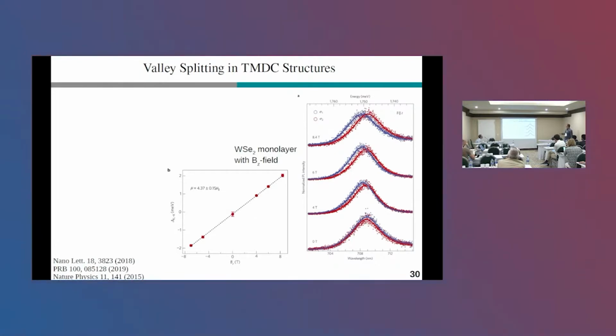Once you crank up the external magnetic field in the out-of-plane direction, you will find a very nice splitting of these two peaks, which is known as the valley splitting. And this valley splitting follows a linear trace as a function of the magnetic field. Also the g factor plays a heavy role. In the case of bare monolayer TMDCs, this g factor value is around 4. But still, if you apply a magnetic field of 8 Tesla, you get only a valley splitting of 2 millielectron volts. And this is where the proximity physics comes into play.